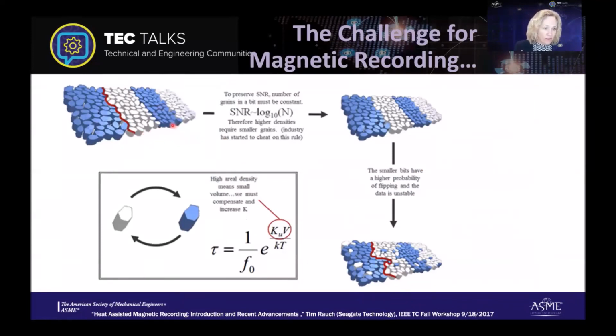What's been the challenge for magnetic recording is really this scaling that needs to happen in the disk. So this is the recording, the little track of recording media. We have the 2 blue and white indicate 2 different magnetizations. So let's just say that blue is south to north up, and white might be south to north magnetization down. And the drive is actually detecting the absence or presence of transitions between the 2 magnetizations. And so as we make the track smaller, if we don't make the grain smaller, you can see that this transition relatively becomes wavier and wavier, and that would actually contribute to noise. And so to be able to keep the signal to noise constant, as we scale down the bit, we need to scale down the grain.